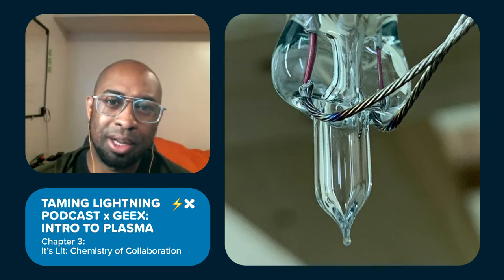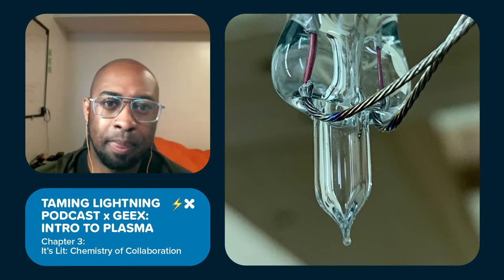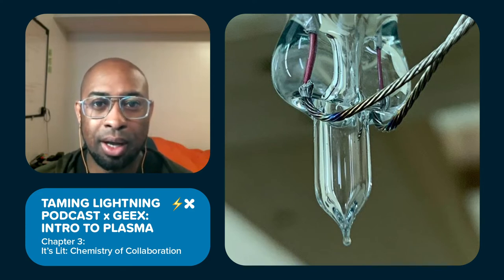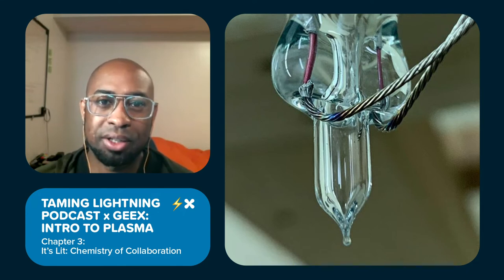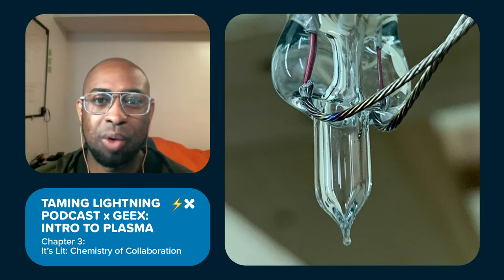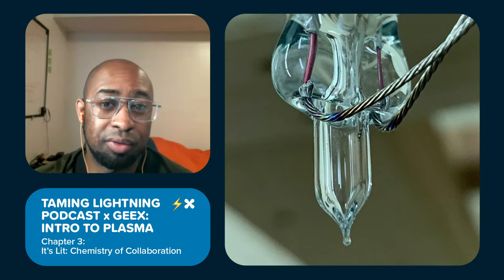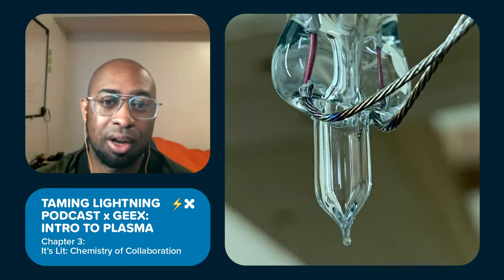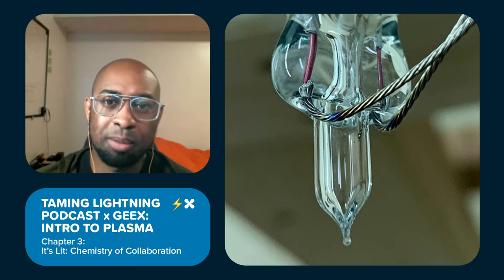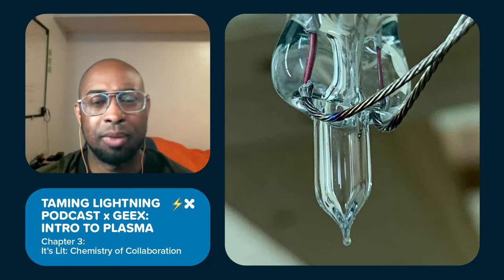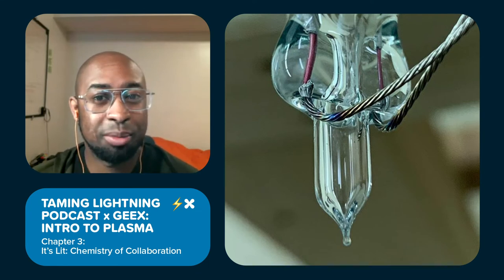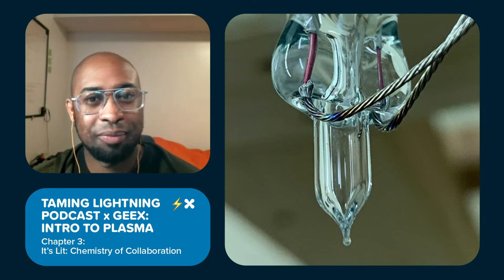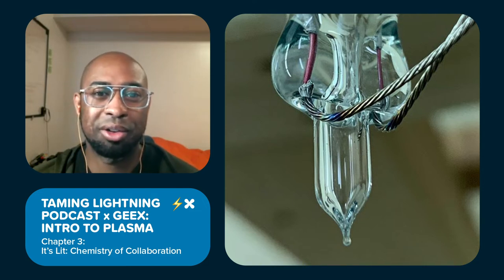Now, after the first tip-off, assess the health of your filled plasma vessel. Light up the piece using your transformer. Confirm your filled vessel is healthy. Has there been any shift in color effects, or is your piece becoming too hot to touch? Are you experiencing any issues? If you're experiencing any issues, revisit some of the pre-filling checks we discovered earlier. Make sure your tip-off was executed well. This could be another challenge for beginners. This can also lead to possible leaks at your tip-off. So if you tipped off the first time, well, you have an option to refill if you find yourself with a little bit of a leak.